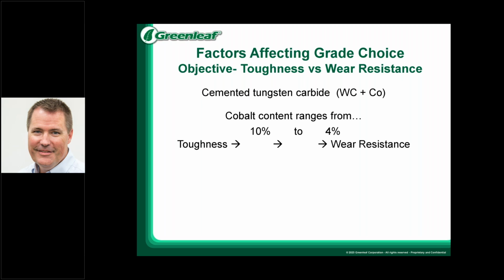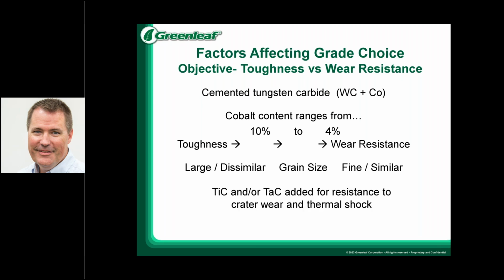with the grain size and the amount of cobalt that is in there that plays into whether the grade may be tougher or more wear resistant. Typically, with a higher cobalt content, you're going to be dealing with larger carbide grains versus where you can reduce the amount of cobalt, so there's less cobalt that can be present in the matrix with a finer grain carbides. In addition to the carbide size, you could add other elemental carbides as well, with titanium carbide or tantalum carbide, which can help with the shock resistance or the heat resistance of the carbide grades as well.